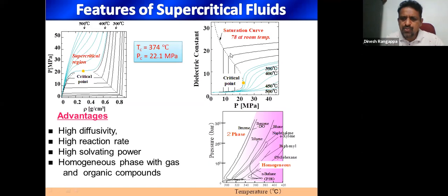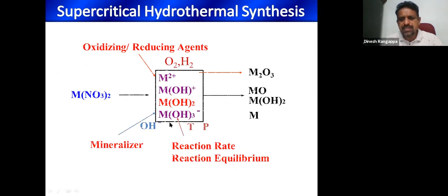So under this supercritical condition, water forms a homogeneous mixture with organic solvent. This kind of reaction medium provides a unique environment to conduct organic and inorganic hybrid reactions, and to make nanomaterials coated with carbon, conductive carbon, or some organic modifiers or polymers. With supercritical fluid as a reaction medium, we can achieve high diffusivity, high reaction rate, high solvating power, and a homogeneous phase with gases and organic compounds when we synthesize nanomaterials. Hence, we utilize this technique and developed it for energy material synthesis.